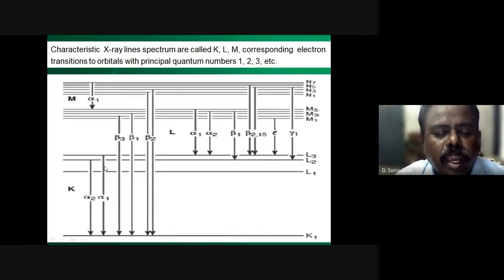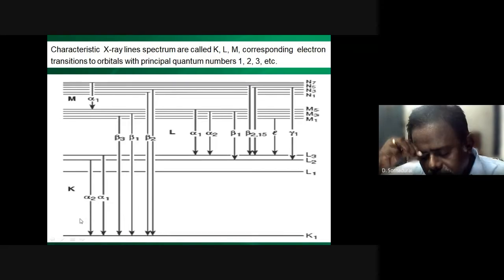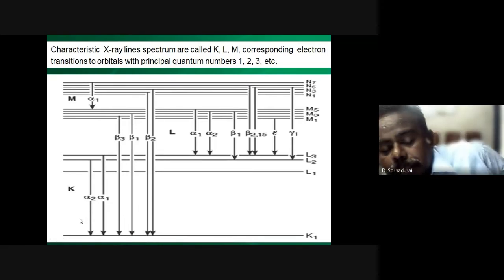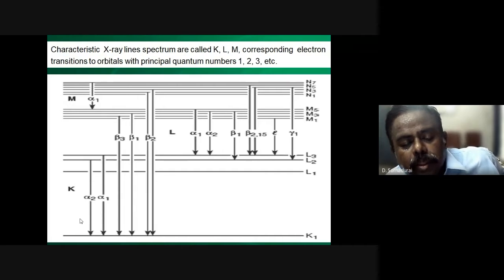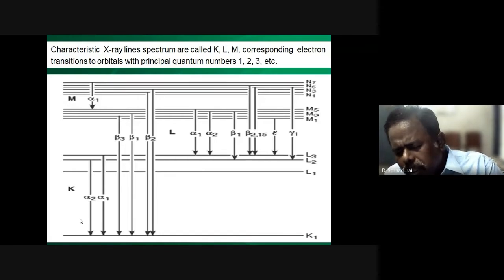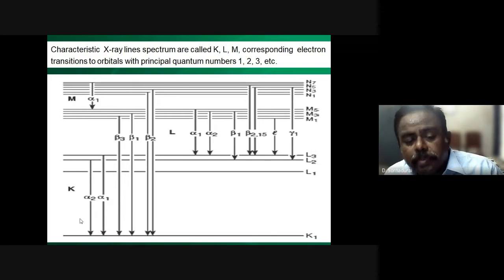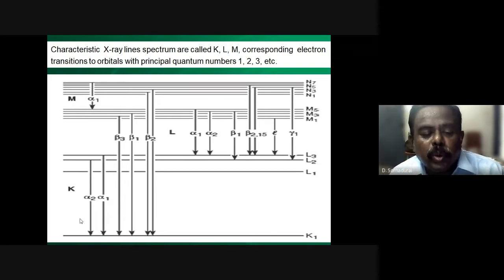Now, you could see the difference between the K alpha 1 and K alpha 2 energy level split. K alpha 1 is coming from L3, and K alpha 2 is coming from L2. This is the reason that the intensity ratio between K alpha 1 and K alpha 2 will always be 2:1. K alpha 1 will have higher intensity compared to K alpha 2.